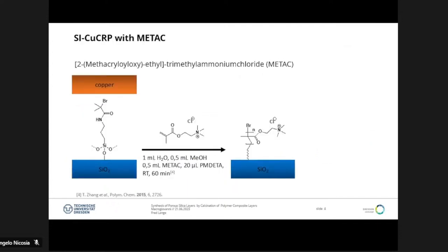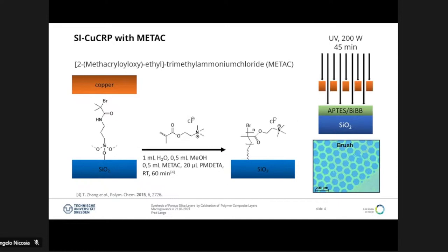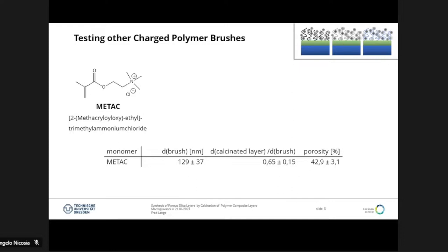The surface-initiated copper-mediated controlled radical polymerization I mentioned on the last slide is shown here. Therefore, we use a copper source, the copper plate, which is fixed at a distance to the substrate. With that, in a facile way, thick polymer brushes can be achieved, like 180 nanometers in 1 hour. And with photolithography, even structured brushes can be achieved. In the first step, I did the reaction with my standard monomer, which is shown above, 2-methacryloyloxyethyl trimethylammonium chloride, and I achieved porosities of 43%.